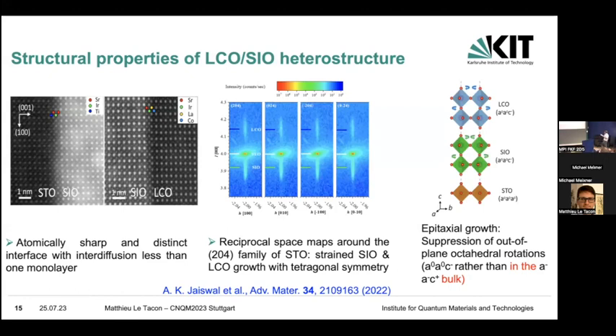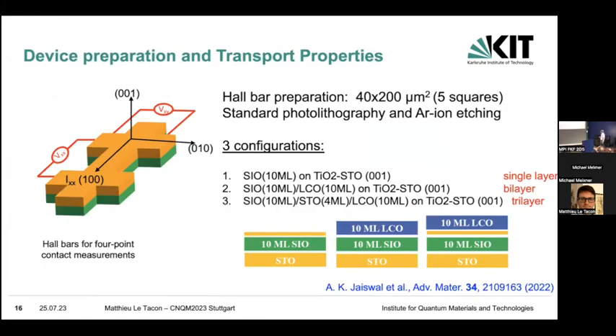for 10 monolayers typically, the iridate and the cobaltate layers are fully strained to the substrate, and we actually suppress the out-of-plane rotations, while the in-plane rotations remain, and we have really a pseudo-tetragonal unit cell here. And so what we did is to make a Hall bar from this to be able to measure the longitudinal and transverse conductivity.